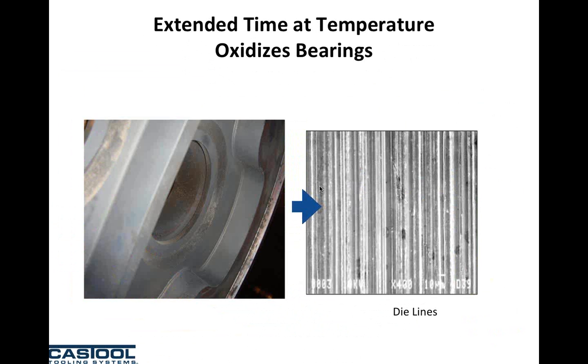Unfortunately, the die bearing, being an EDM surface, attracts oxides faster than any other item in the die oven. Another big problem, just to touch base on it, is the adhesive layer on the die bearing. A lot of people put fans in their die ovens, and the fan's job is to pull the air of the factory and push it into the die oven to heat the dies quicker through convection. The worst thing you can possibly do is take the dirt from the factory and push it into your die oven, because it's going to end up in your die bearings.